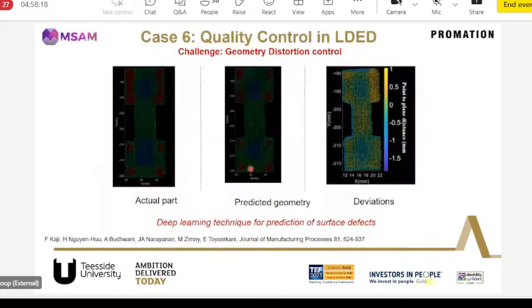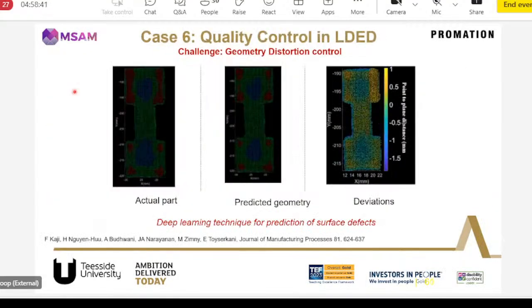Another project that we did was on quality control on LDED. So we were trying to use deep learning to predict the surface defects. In additive manufacturing, you can see there will be variation in the surface quality. You can see here there are these sort of dips and highs and lows on the surface. The surface quality depends again on the process parameters, the standoff distance, and a number of parameters govern that. So we developed a deep learning technique. One of our PhD students developed this deep learning technique for predicting surface defects.